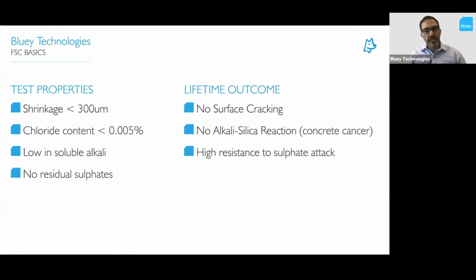So all of this leads to us looking at how we can determine the 100-year design life. And there's a lot of factors that we've tested and put forward as reasons for making that assertion. So the shrinkage on the product, as I mentioned, is less than 300 microstrain. We have a very low chloride content, so we know that's good for the steel reinforcement, less than 0.005%. It's low in soluble alkalis, and we have no residual sulfates.